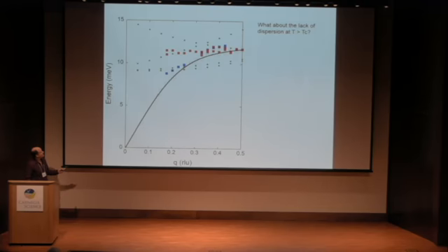Well, the point is that there are many Bragg peaks involved. It's not just one. There's just an enormous number of them, and only a few are shown here. So here's the one I was telling you about before, 2 minus 4, 0. It comes up like this, but it touches base here, so you can get this sort of flat mode here. Here is 3 plus or minus 3, 1. So the two of them, it comes in like this. This can give you a flat mode here. And then the low temperature stuff can be fitted by something like 2 plus or minus 2, 2.